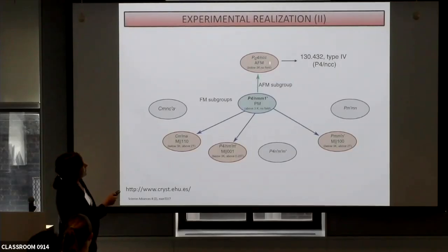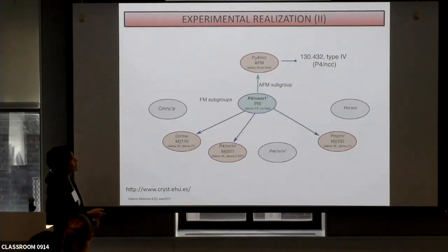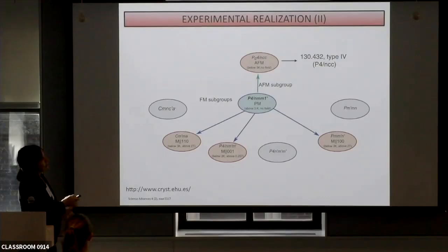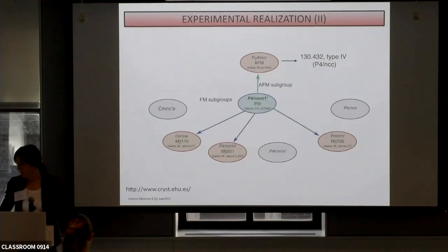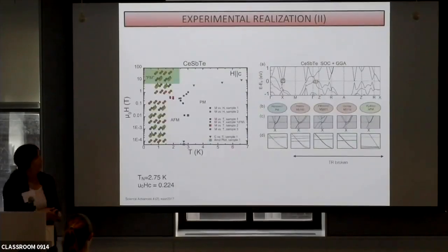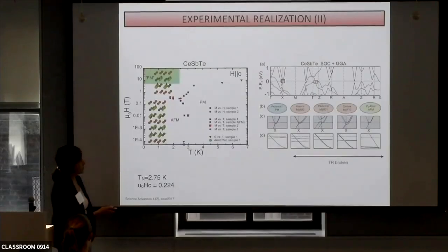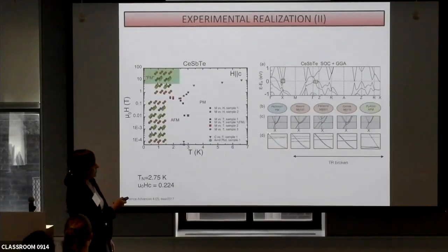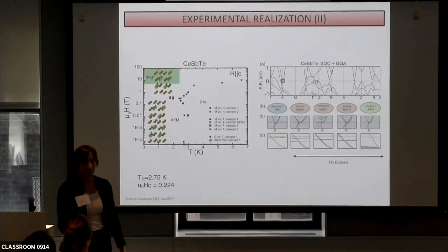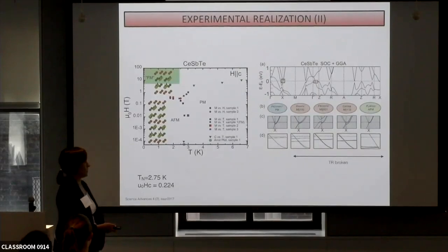Below the Néel temperature and with no field, we find an antiferromagnetic phase, and this ferromagnetic phase is a type of magnetic material. So DFT calculations at the same high symmetry point, but for different magnetic phases, give, of course, a different band structure. So the paramagnetic one, for example, at X has a 4-fold degeneracy. If we add the magnetic field in the direction 111, it splits.